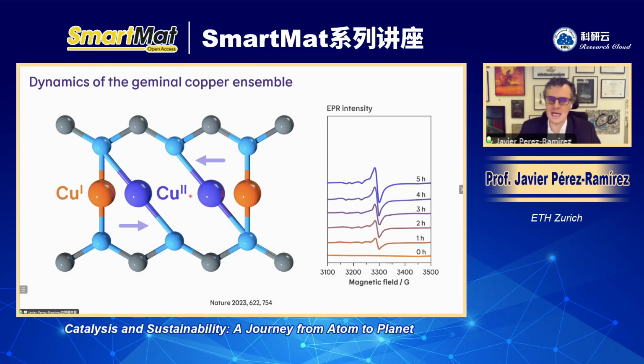And so what happens when you put the reactants actually is that a copper 2 signal starts to appear. And the copper 2 signal is actually the oxidation state of copper when it shuttles from this nitrogen atom to this nitrogen atom, and this nitrogen atom to this nitrogen atom. And this is a 2.46 angstrom distance. You can see the development of a copper 2 signal, which is active in EPR, after 5 hours of reaction time in the cross-coupling.